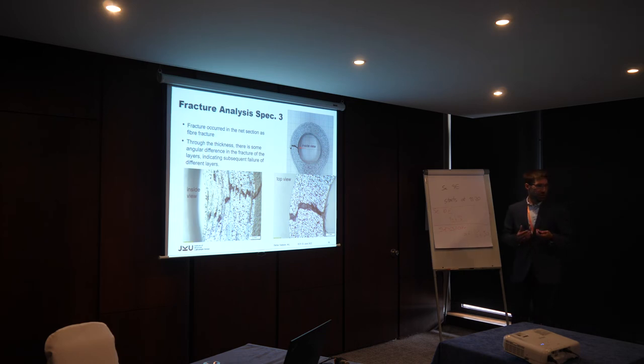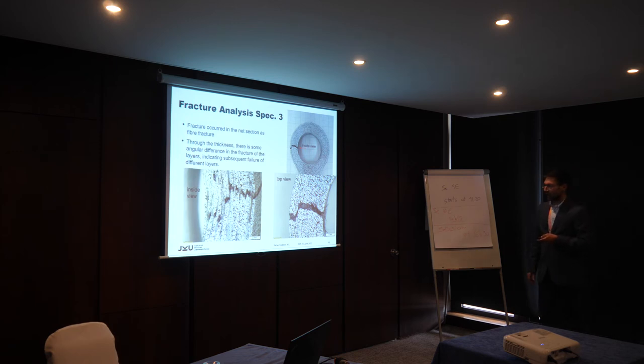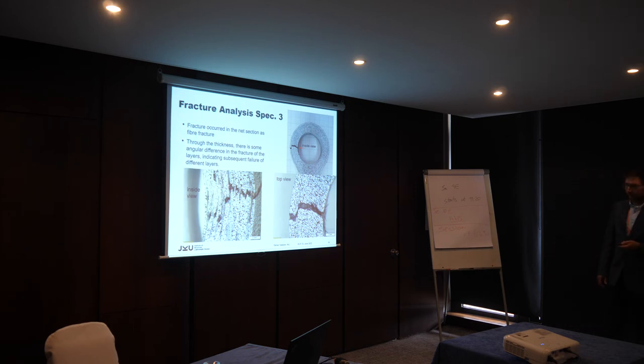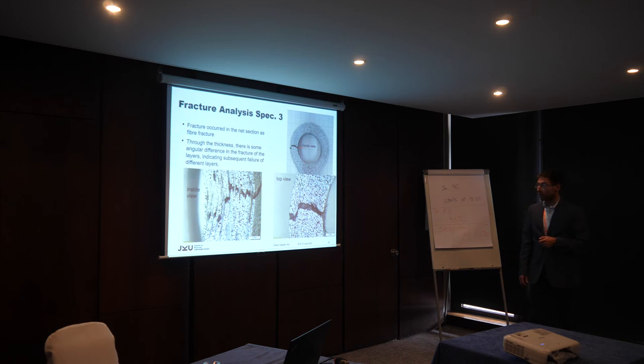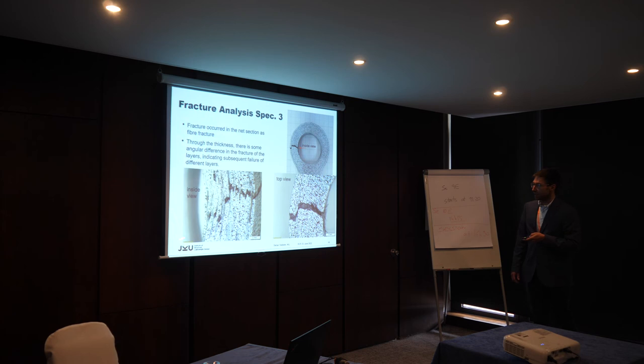Our next steps are to perform CT scans and find out what was really behind that, then go into modeling to see if we can find a model that explains our behavior — potentially some weaker layers or a slight waviness — to explain the change in fracture from the standard expectation to this subsurface fracture we experienced in both specimens. For comparison, one other specimen with a different material that we already CT scanned shows what fracture should look like.